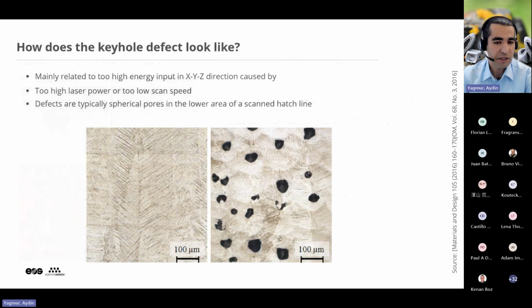And if there is too much energy on the other side, then we see instability of the keyhole, causing more sphere-like defects. Sometimes I see that these are called keyholes, and keyhole is not desired. This is not exactly true. Keyhole defects, which come from the destabilization of the keyhole, are not desired. The keyhole itself, a stable keyhole, is the heart of our process.